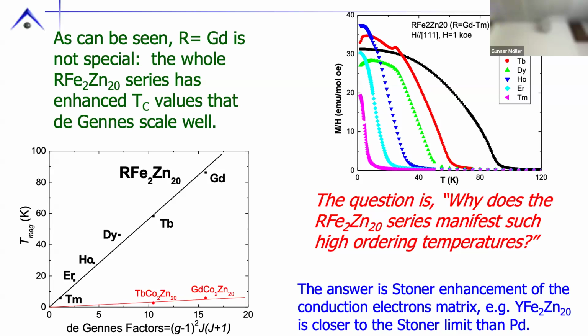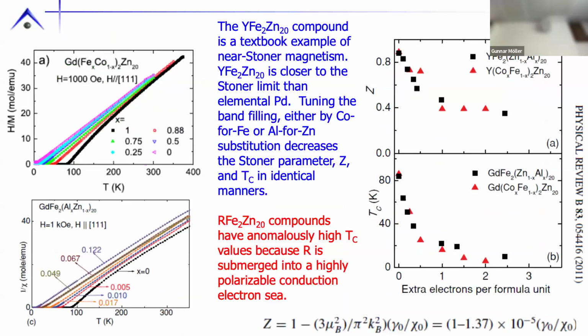The question, of course, then is why is the rare earth iron 2 zinc 20 series manifesting such high ordering temperatures? And the answer, going back to it's not moment bearing, is we are really close to the Stoner limit for yttrium or lutetium iron 2 zinc 20. And I can show you that.